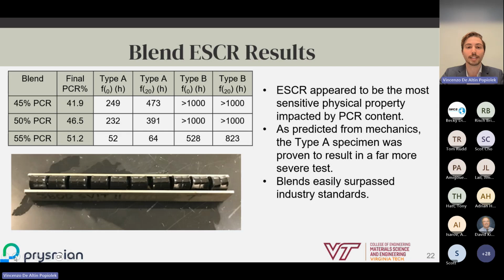Specifically looking at the Type B sample, which is what it would be compared against, we see that the 41.9% and the 46.5% PCR samples were able to surpass more than 1,000 hours with 0 failures, and that our 51.2% sample was able to surpass 528 hours with 0 failures, again, more than 10 times the industry standard.